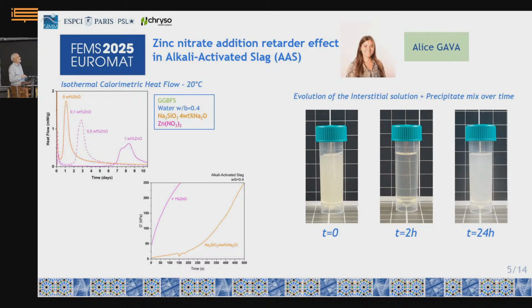And actually, this can be related to this. What we have observed is that I have my alkali sodium silicate solution. I put zinc nitrate in it. I precipitate something. And this precipitate, I don't have the data here, contains zinc and silica. So it's amorphous, so we still have to analyze exactly what it is, but this is mobilizing a large part, 20% of the silicate concentration initially in solution, in the form of a solid, okay? And as a solid, we don't have this gel formation because we have depressed the silicate concentration. But this gel here is metastable, and it redissolves after a while, and the reaction proceeds again.